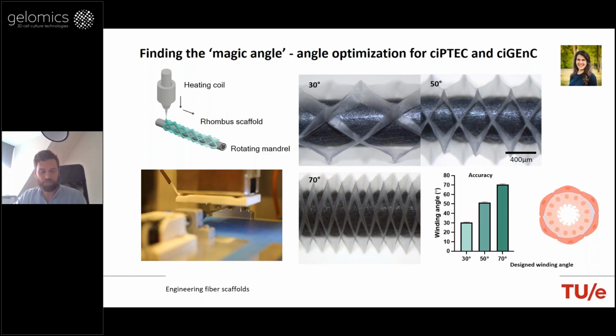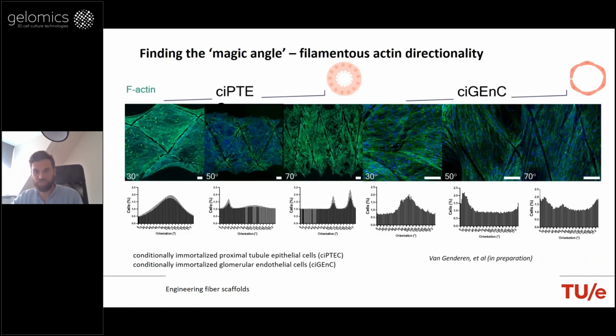So we succeeded on creating these tubule constructs with different winding angles, now out of polycaprolactone again, not the silk as I introduced to you. What was interesting to see was that both the ciPTEC and the endothelial cells formed tight and homogeneous monolayers within the tubular scaffolds and generated collagen 4 enriched ECM matrix. I don't want to bother you with all the details, but what you can see here is that the 30 degrees winding angles induce the preferential alignment for the ciPTEC cells.